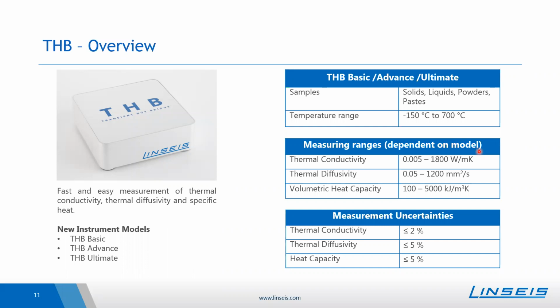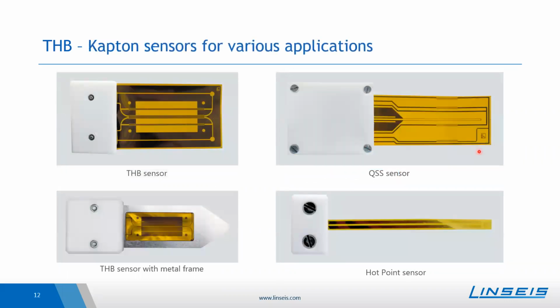As the instrument allows the measurement of a broad range of thermal conductivities, we need some different sensors to realize that. We have on the one hand Kapton-based sensors for the measurement up to 200 degrees Celsius, and we also have some ceramic-based versions which allow then the measurement up to 700 degrees Celsius.